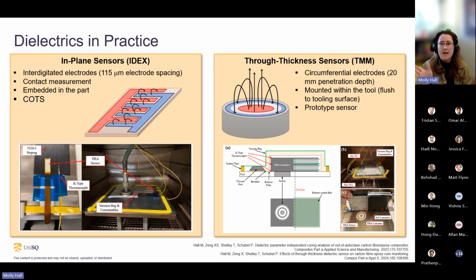The other type of sensor, and we'll ignore the through thickness statement there for just a minute, are tool-mounted monotrode sensors, which are like the one I'm showing here. They're mounted into the tool, they touch the surface of the part, but commonly these sensors are also only taking a contact measurement. The unique part of the sensor I used in my PhD is that it actually can make a reading through the entire thickness. So based on the design of the sensor, you have the circumferential electrodes that cast an electric field. For this one specifically, it was designed for a 20 millimeter penetration depth.